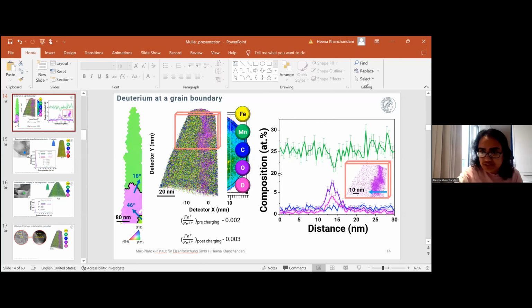This was done because here I was trying to charge the atom probe specimens. In that gas charging chamber, we can go to only very low pressures, like 250 millibars, and at those low pressures you cannot charge the bulk samples. Also in that chamber, we cannot really introduce the bulk samples. So that's why I had to do it on atom probe specimens. But the tritium charging was possible on bulk samples at Karlsruhe. That's why it worked.